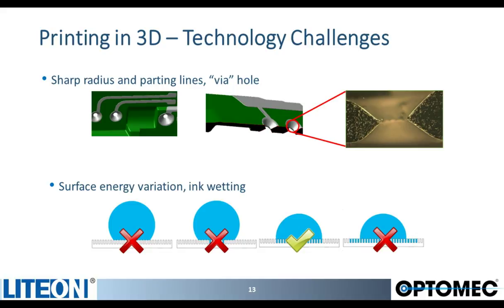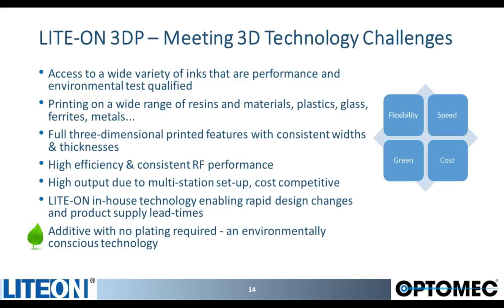The substrate will have different surface energy depending on the plastic type and also on the molding condition and handling. To get the needed printing result, we have to be absolutely sure we have the right wetting of the ink. Effort was spent to optimize the process and the ink to be sure that we get uniform wetting in all areas of the part. So that was some of the challenges we have been working on and solved.